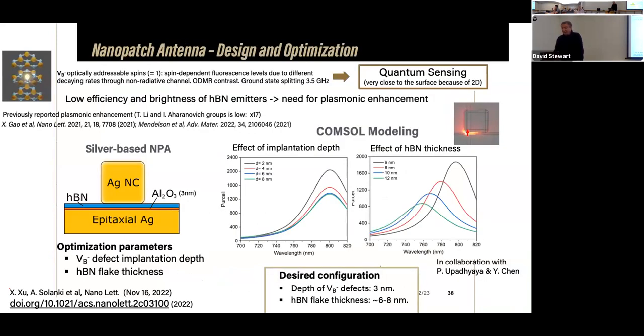Let me also briefly mention our collaborative work on using hBN, because hBN is also known to have good single-photon emitters, in this case particularly the boron vacancy. Why is it so attractive? Because it has a spin, and since it's basically a 2D or quasi-2D material, you could go to very close proximity to a sample which you'd like to probe and measure, for example, magnetic field. So what we did, we placed this hBN between the silver crystal and the epitaxial silver, but first we did a simulation of what is the optimal size of this film and where the defect should be located. It turns out that the optimal thickness for this hBN would be around 6 nanometers, and the defect should ideally sit somewhere in the middle, and that's what we did.